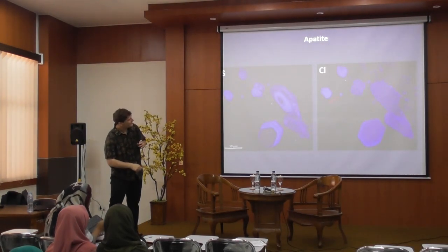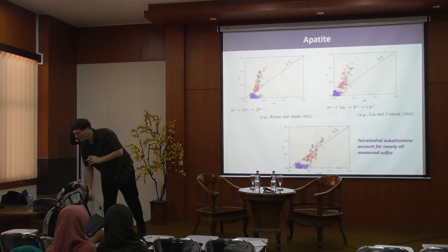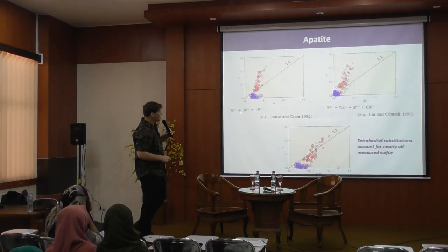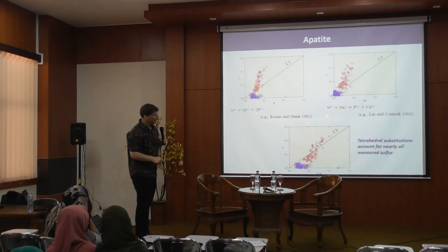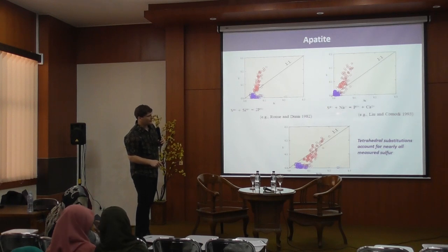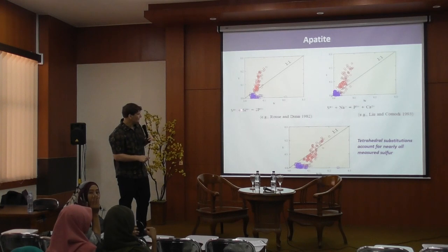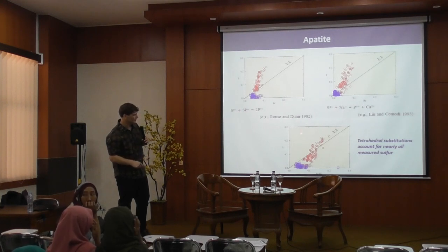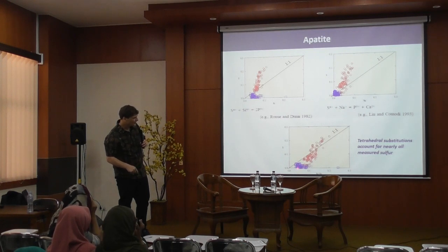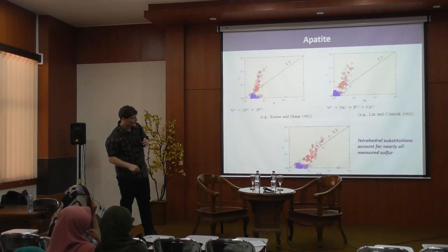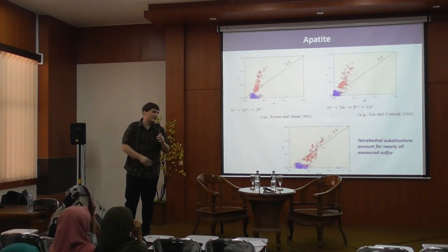Again, some more maps, you see this sulfur zoning. And so we looked at coupled substitution mechanisms. If sulfur is going into these tetrahedral sites, substituting for phosphorus, you can have coupled substitutions with silicon to get a charge balance, right? Or you could have coupled substitutions with sodium to achieve charge balance. And if you sum up these two potential coupled substitutions, looking at these minor elements, sodium and silicon, you actually account for most of the sulfur that's in these apatites. That's a one-to-one line, so this would be 100%. If 100% of the sulfur were in these tetrahedral sites, you'd be along this one-to-one line. If you sum these two substitutions, we're a little bit off, but we see that probably this is where the